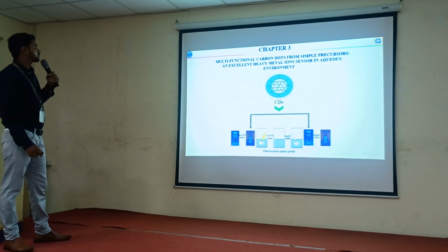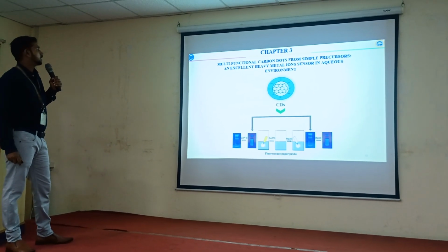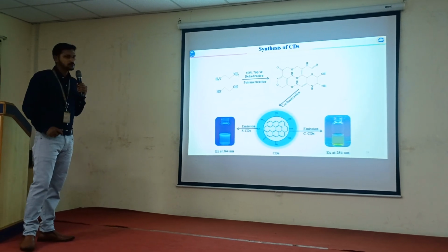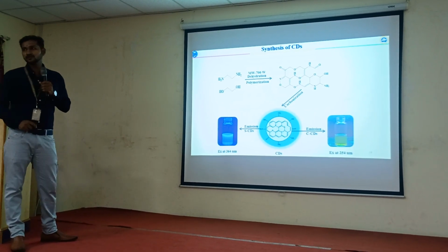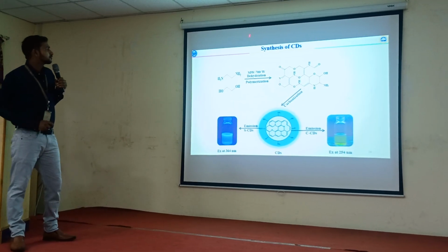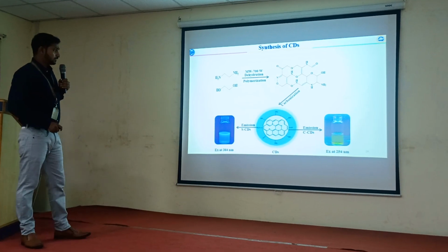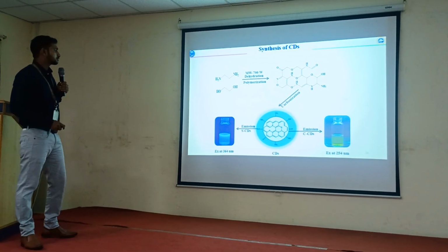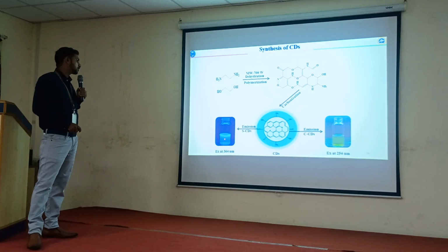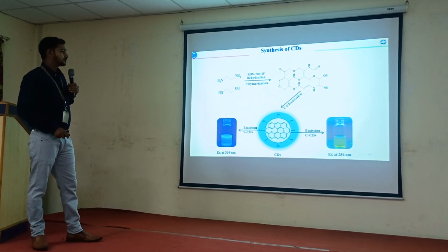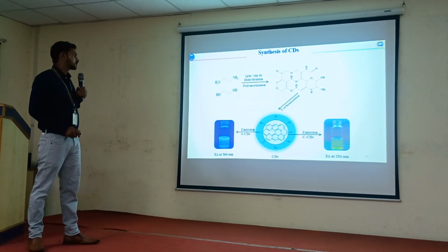And chapter 3, multifunctional carbon from simple precursor and excellent heavy metal ion sensor in aqueous environment. Synthesis of carbon dots. The carbon dots are synthesized with ethylenediamine and ethylene glycol with the help of microwave irradiation at 700 watt for a time period of 10 minutes. The resulting carbonized product of carbon dots dissolved in water gives a bright blue color emission under 364 nanometer and dull emission under 254 nanometer excitation light.